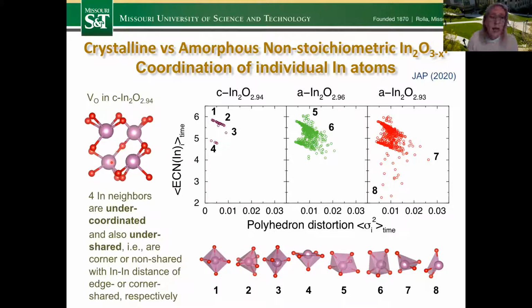and the electronic properties. So we are looking not only at the coordination, distances, distortions, but also looking at the nearest neighbors and sharing between the different nearest neighbors. So here we can see that if the vacancy in the crystalline indium oxide creates nearest neighbors that are becoming 5 coordinated, down from 6 in a perfectly stoichiometric indium oxide, we have a huge fraction, about 30% of all the atoms in amorphous, that are structurally similar, at least in the matter of the local structure, the coordination and the distortion, to that vacancy surrounding.